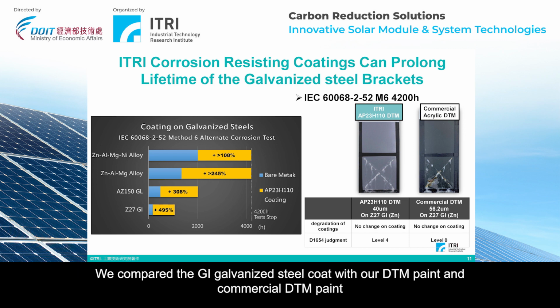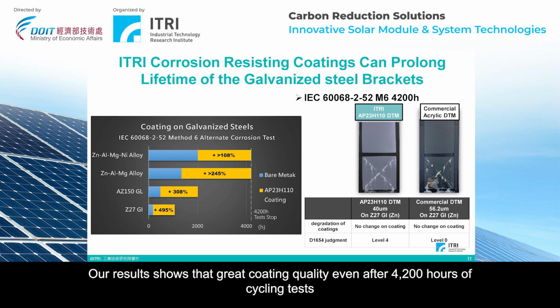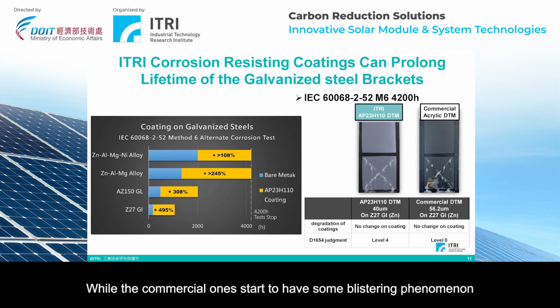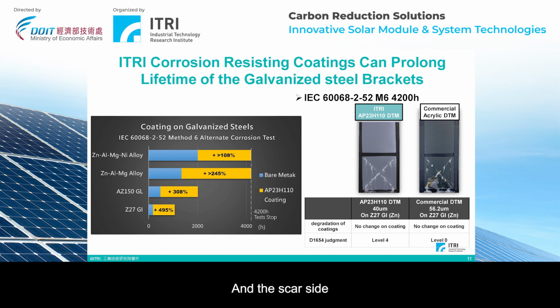We compared the GI galvanized steel coated with our DTM paints and commercial DTM paints. Our result shows a great coating quality even after 4,200 hours of cycling test, while the commercial ones start to have some blistering phenomenon, which tells the interface changing between the coating and the steel. And at the scar site, some brown rust can be observed. There will be a huge risk if applied in the real world.